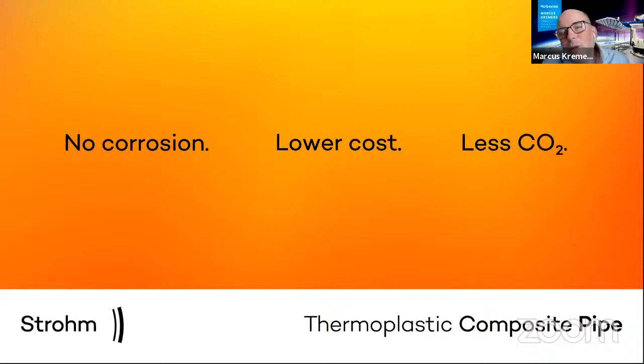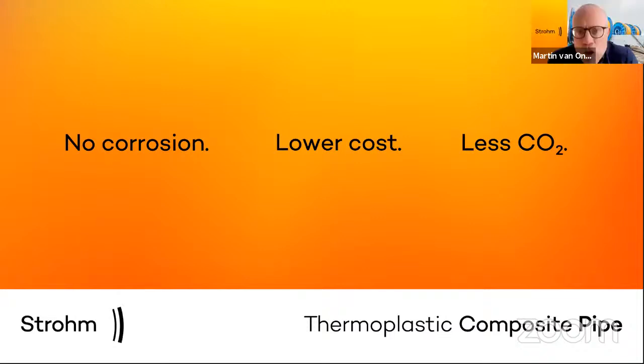Okay. Good. And then I have a question from Mr. Nishiyabu. He asks, what about the orientation of the carbon or glass fibers in TCP? What kind of orientations do you use? Yes, that's also a very good question. Depending on the requirements, if we have a flexible pipe that does not need high tensile strength, then we use plus or minus 55 degrees. However, we change it slightly through the wall of the pipe so that we avoid a stress peak, and we can handle the highest pressures and even have the fibers on the outside still carry a lot of load. So we typically move from 60 to 50 degrees, but on average it's 55 degrees.